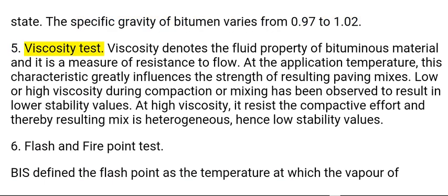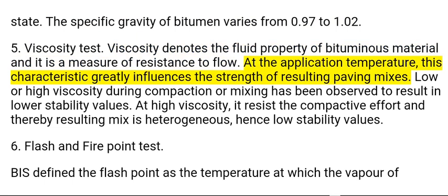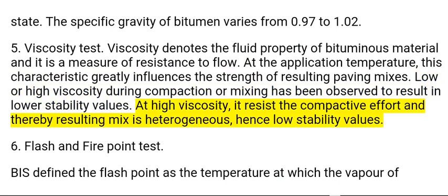5. Viscosity test. Viscosity denotes the fluid property of bituminous material and it is a measure of resistance to flow. At the application temperature, this characteristic greatly influences the strength of the resulting paving mixes. Low or high viscosity during compaction or mixing has been observed to result in lower stability values. At high viscosity, it resists the compactive effort and thereby results in heterogeneous mixes, hence low stability values.